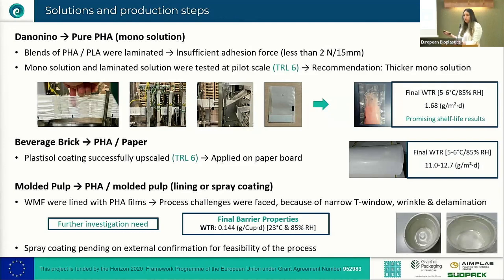Also, we tried a solution with lamination, but we saw the same problem as with the pure PLA solution. We have difficulties with the adhesion between layers. Therefore, we rethought the solution and said, what about making a PHA, but a little bit thicker, and overcome these problems? And we successfully did this and produced mono PHA and made some pouches, as you can see here, with promising shelf life test results.